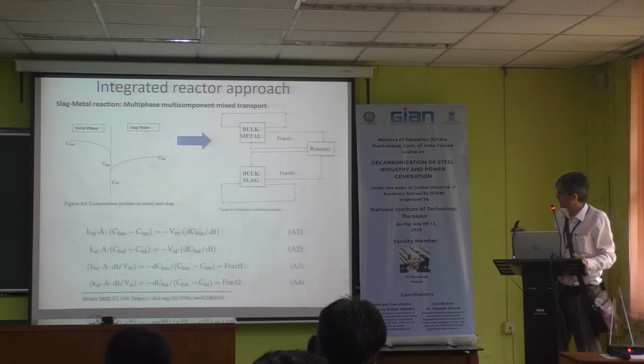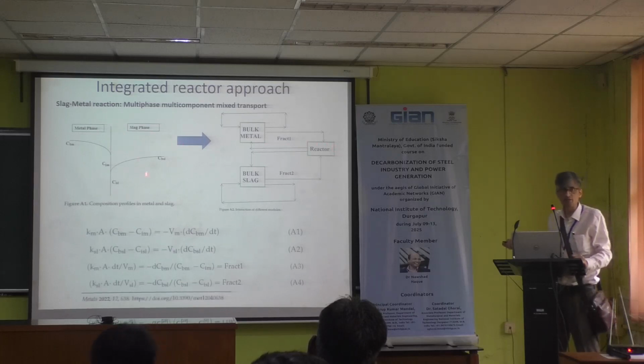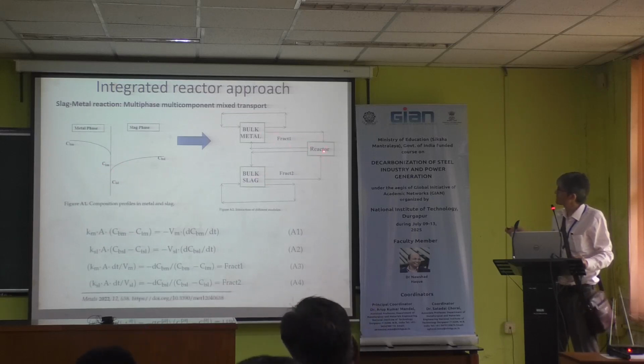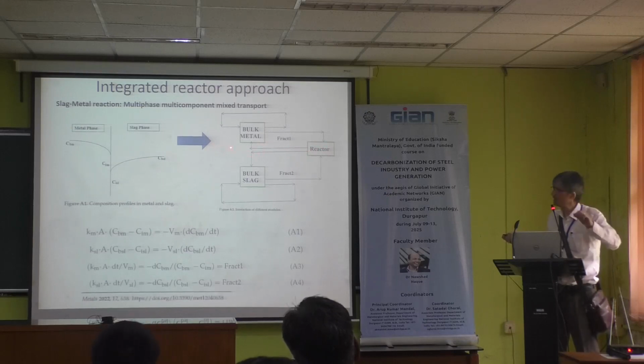So there would be multiple reactors, for example, bulk metal and bulk slag. They may be non-equilibrium reactors, but there could be an interface which is in thermodynamic equilibrium, because at high temperature the interfacial compositions will always be in thermodynamic equilibrium. That means these two compositions can always be regarded as being in thermodynamic equilibrium. So this interface will be represented as a thermodynamic reactor, and the flow of streams could be defined at every time step in a certain fraction or certain rate, related to the mass transfer coefficient. So this is for a slag metal reaction.